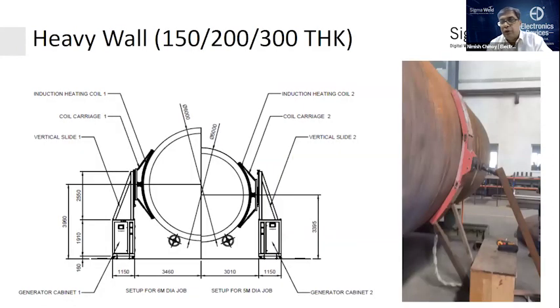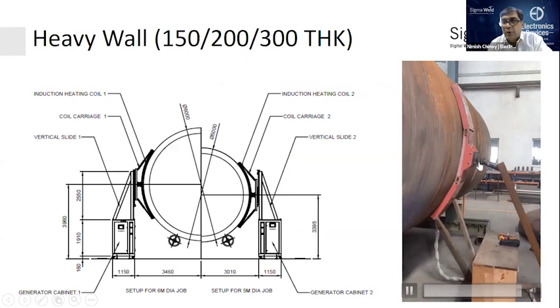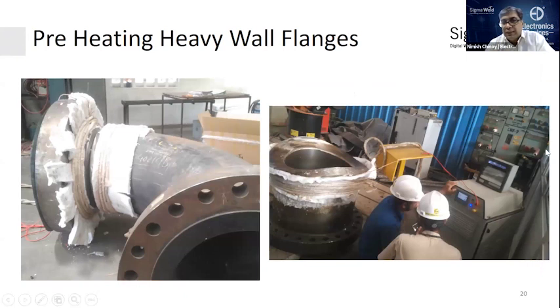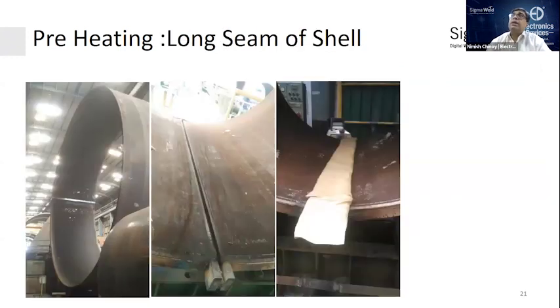cool in the air. If you had a very big job setup, you could use flexible C-type coil, which allows the job to rotate, and you can put it from one side and heat the job. Same thing goes for very heavy vessels. This is when you are doing it for the lip of the flange here, for the flange joint. These are almost 200 thick. These would have taken 4 hours to set up on a normal gas-based burner or an electrical resistance heating. In induction, this can be done in 30 minutes. So the cycle time saved is very large.